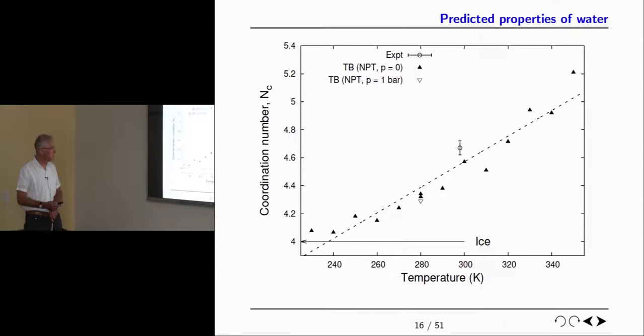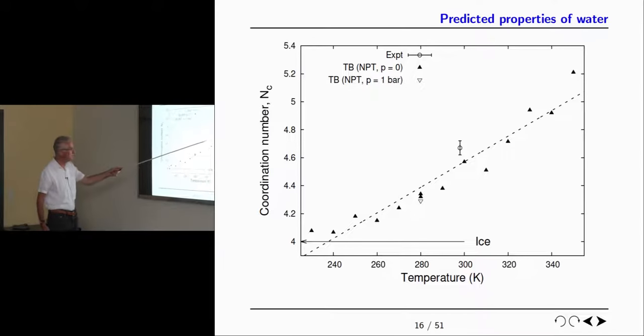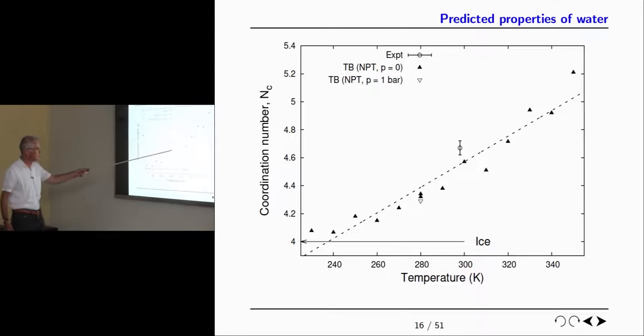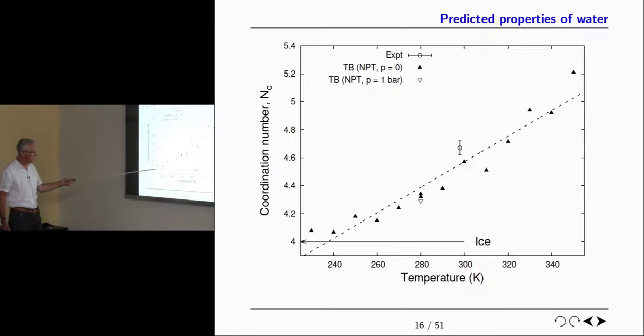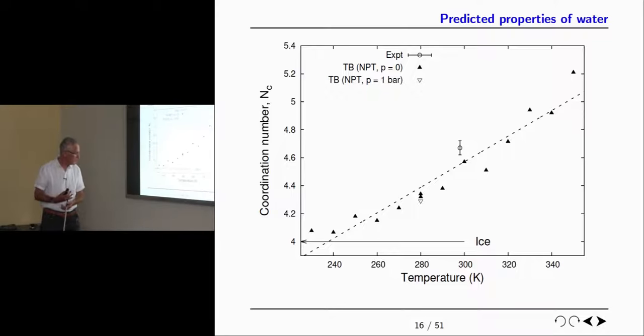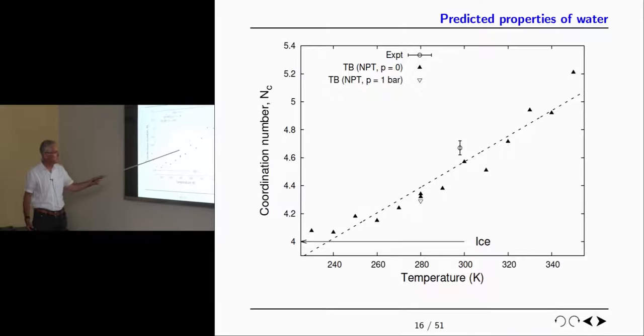This is the coordination number, the famous fifth neighbor. Here's an experimental data point of the coordination number of liquid water as a function of temperature, and you can see it kind of heads down and becomes less coordinated, and this is the value for ice, exactly 4. So this is twice the number of hydrogen bonds per water molecule. So in a perfect covalent network like that, every water molecule has 4 neighbors, but in liquid water that's not the case, and that appears to increase with temperature, as we found in our calculations.